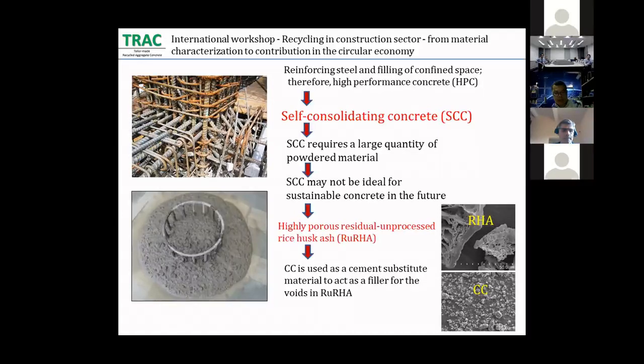Three different particle sizes of calcium carbonate were used to replace Portland cement at 20 and 40 weight percent, while rice husk ash replaced fine aggregate, natural sand or river sand, at 20 weight percent. As you know, currently concrete structures require a greater density of reinforcing steel and filling of confined spaces. High-performance concrete is required to achieve this condition. One important type is self-consolidating concrete, or SCC, which can enhance workability, high-flowing characteristics, and strength development without increasing segregation of concrete material during transportation, placement, and packing.